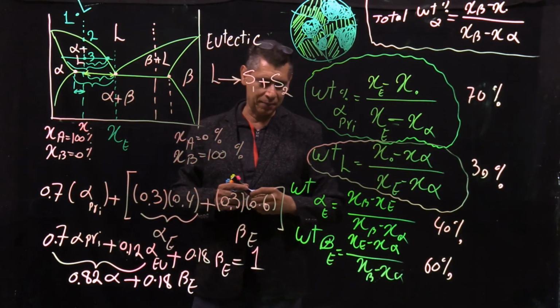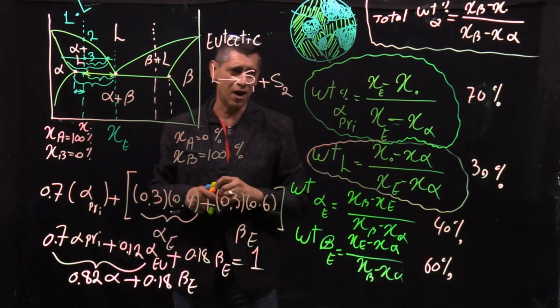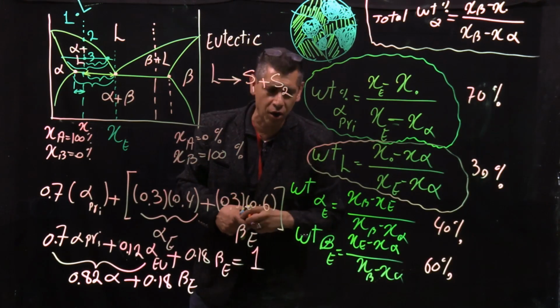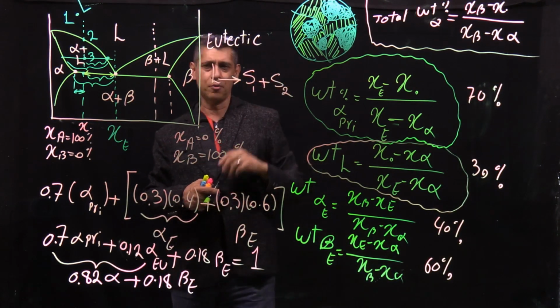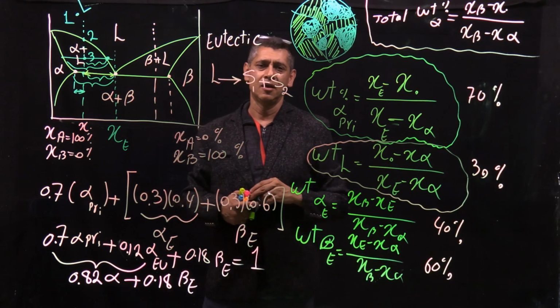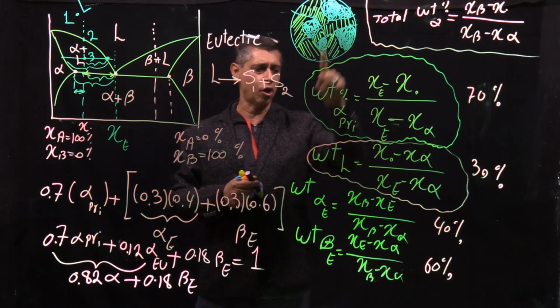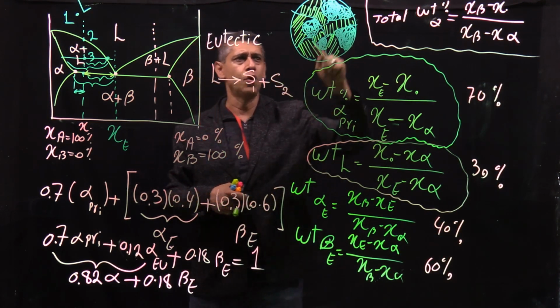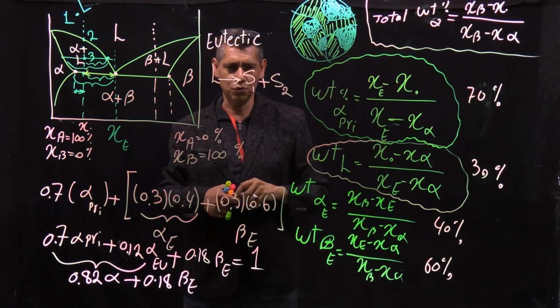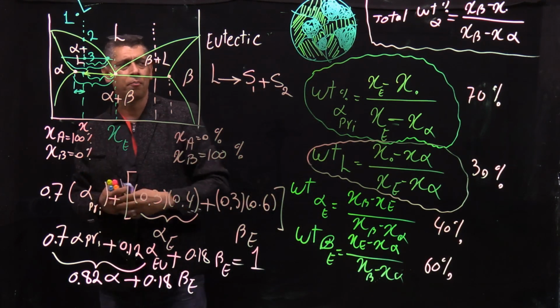So for example, in carbon iron, you look at the amount of primary alpha you have, and by knowing how much primary alpha you have, you can simply go and calculate, with a good approximation, the carbon content of this alloy. So therefore, not always are you interested in knowing in total how much alpha you have. Most interesting is how much primary phase you have. From the primary phase, you can go and calculate what the composition was.